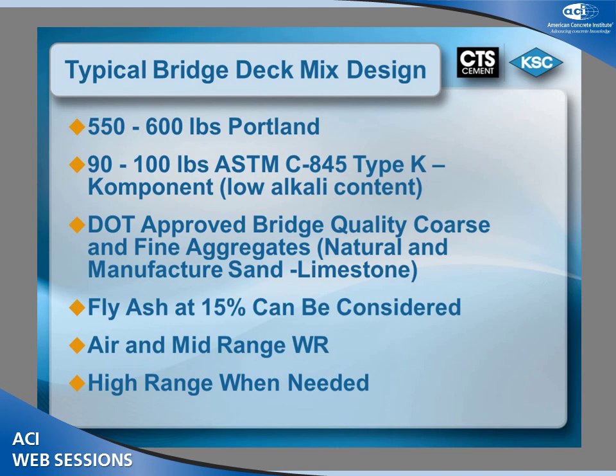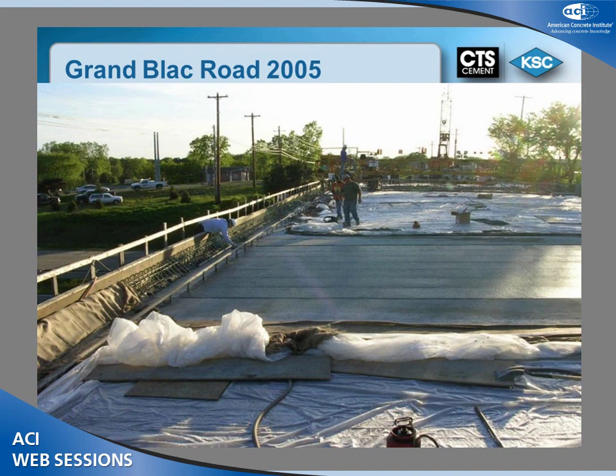Fly ash has been used considerably. I've had a lot of experience personally with the use of fly ash and even some slag, and we can use that successfully, especially in summertime applications where fly ash is a good finishing aid or retardation type of thing in the set times. Air and mid-range water reducers work phenomenally well, and high-range water reducers can be used upon need. And also in some cases, retarders can be used, but again, that's based on what the state's applications are and their permissions.